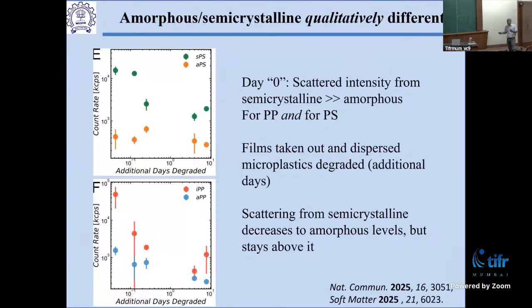But for polymers that have crystals in there, those particles persist and continue to scatter even when you etch it using this nasty piranha kind of etch over a long period of time. So what this tells you is, at least for these crystalline polymers, if you generate particles, those particles stay in the environment for a really, really long time, despite continuing to etch these things over time.